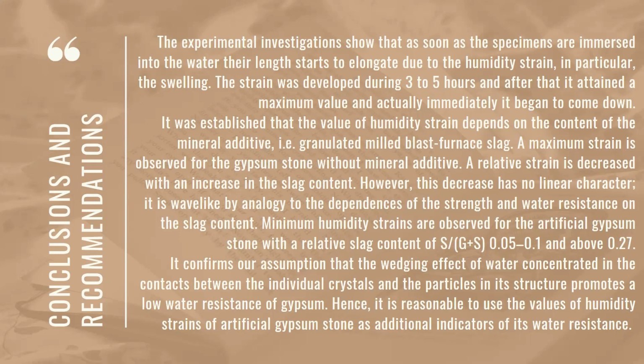Minimum humidity strains are observed for the artificial gypsum stone with a relative slag content, S over G plus S, of 0.05 to 0.1 and above 0.27. It confirms our assumption that the wedging effect of water concentrated in the contacts between the individual crystals and the particles in its structure promotes a low water resistance of gypsum. Hence, it's reasonable to use the values of humidity strains of artificial gypsum stone as additional indicators of its water resistance.